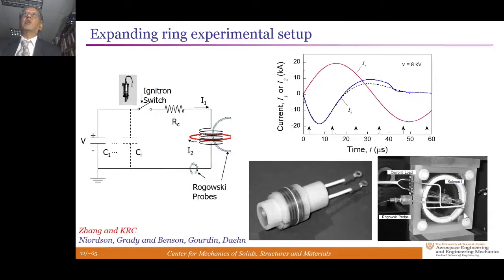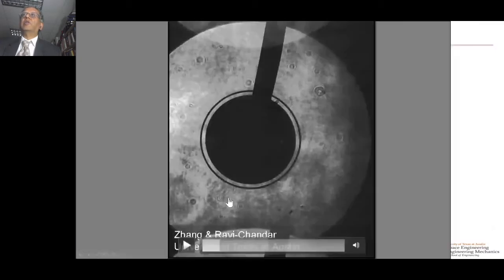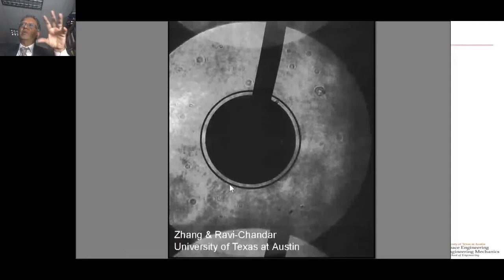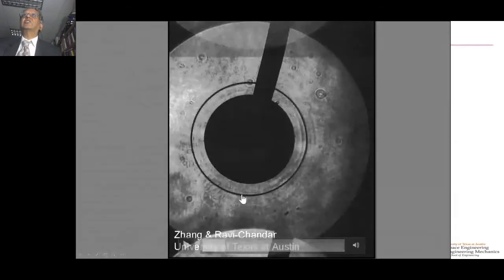This is a shadow of the coil and the housing. The specimen is at the outer perimeter of this. At the first frame, you see that there's uniform expansion. These are very high spatial resolution images that we can expand and see more detail. In the next image, the straining has continued, and you could see that the strain is more or less homogeneous around the entire ring length. And at this point, the ring has broken in multiple locations.